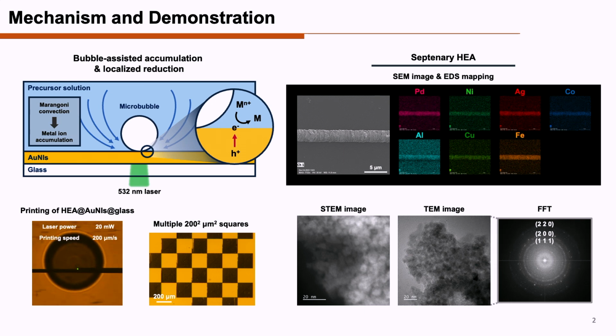For the substrate, we can use glass. It can be FTO glass, like conductive glass. And we will put some gold nanoparticles on it. We usually call them gold nanoislands, and it's a plasmonic substrate. So when we irradiate the laser on this plasmonic substrate, it can generate photothermal effects to increase the temperature in the solution on this substrate. And because of that, we can induce a microbubble here.